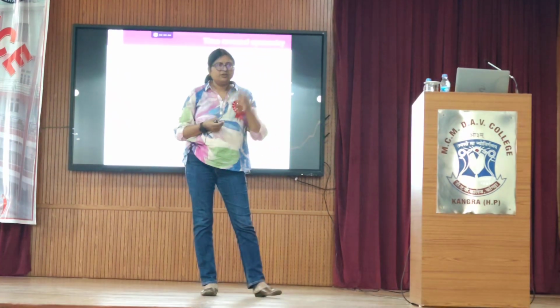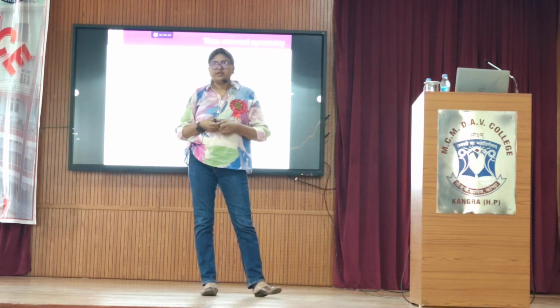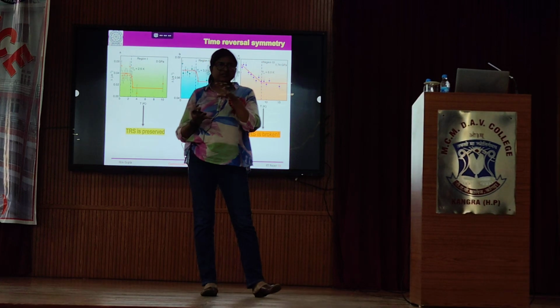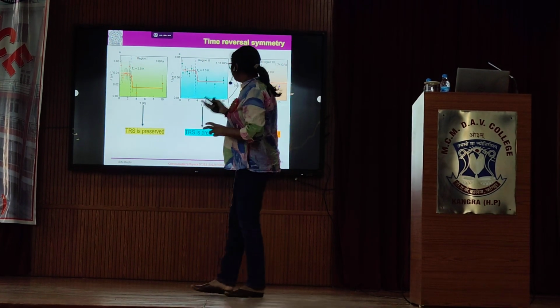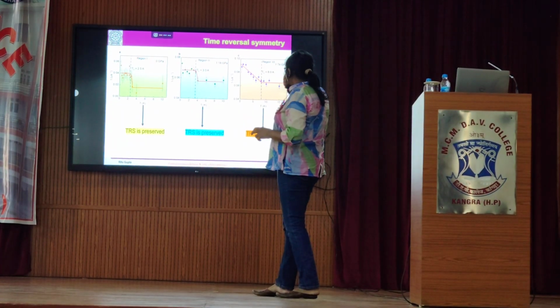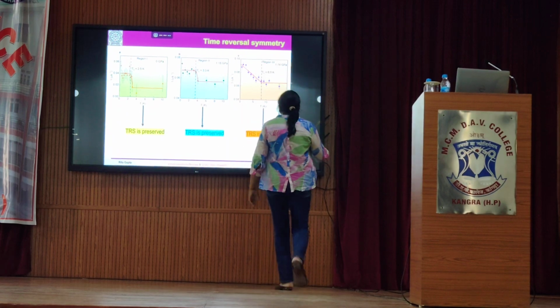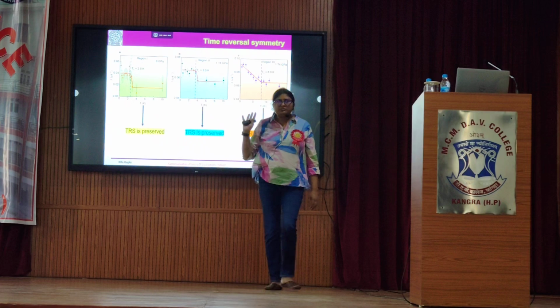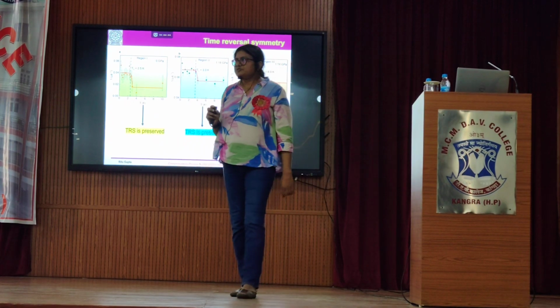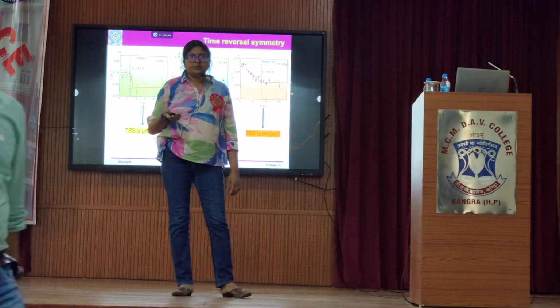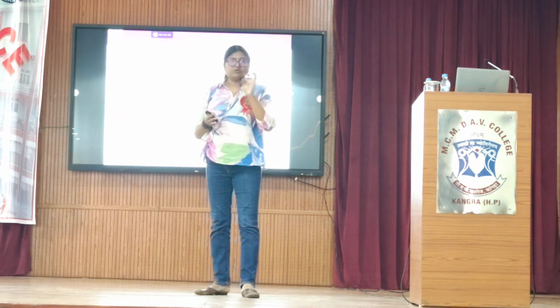Okay? But what if, instead of electrons with opposite spins forming the Cooper pair, you have a Cooper pair with the same direction of spin? In that case there will be some magnetization coming from the superconductor itself, and that can also be probed using this technique. So you can see the change across TC here, and this shows that there is some internal magnetic field present in the system because of some unconventional pairing of the Cooper pairs. Okay? So in principle, by using this technique, we can study most of the things about superconductors. Okay? So these are some in the same category.